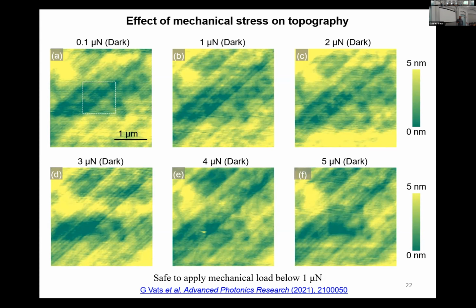But if you focus on this image, you see something here. It's more clear in this. So basically, with the mechanical force, I am actually compressing my material, and we can damage the surface of the material. Having said that, we should be very careful while studying the mechanical impact on these materials, because we don't want to damage our material. We don't want to increase the tip surface contact, because increasing the contact means more charge collection, and that's what we are trying to avoid. So for these measurements, the safe mechanical load was 1 micronewton. So I kept all measurements below this load.